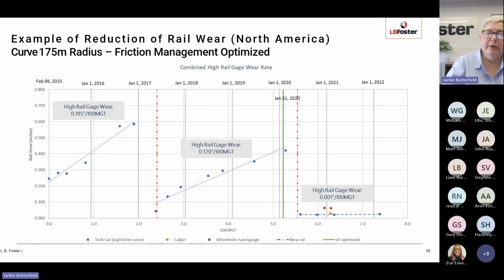Then in January 2020, the whole system was reviewed, and some of the friction management units were moved in order to optimize their position. And shortly after that, there was another re-railing again. So brand new curve, brand new rail. And since then, you can see that actually the gauge face wear is virtually zero. So by optimizing the position of the friction management units, we can achieve a zero wear rate effectively.